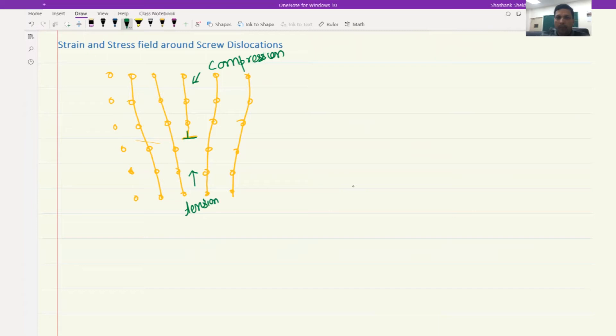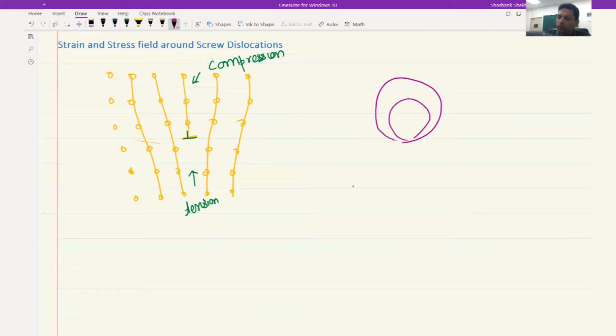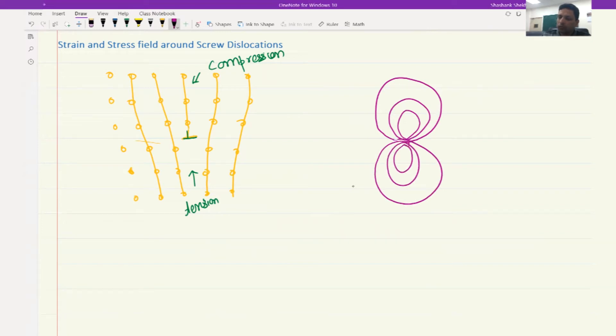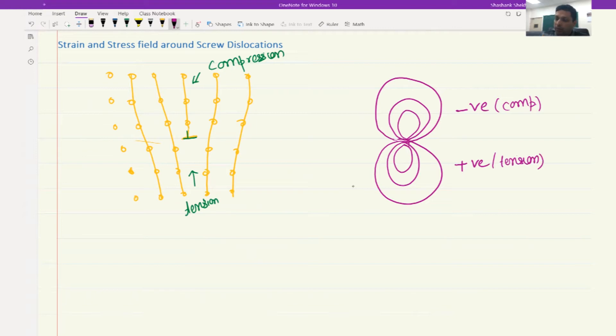When we later look at the equations, you would see that the stress fields would show positive values representing tension on the lower side and negative values representing compression on the upper side. These lines represent contours of similar stresses — much higher stresses but in opposite senses. So this is how the strain fields and stress fields look like for an edge dislocation.